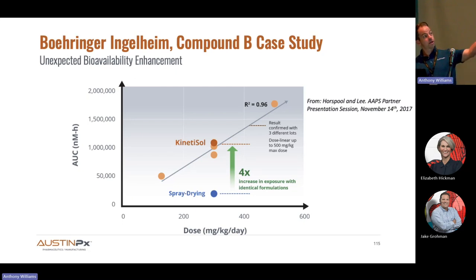But the surprise result of all of this: we were just asked to solve some practical problems. The surprise was when they took our KinetiSol formulation, which was quantitatively identical to the spray dry dispersion, and dosed it at the maximum dose that they were able to administer from spray drying, they got a 4-fold increase in exposure. Obviously, there was some error in dosing or in the study, so they dosed it 2 more times and got the same result. So in triplicate, they demonstrated that the same formulation produced by KinetiSol provided a 4-fold increase in exposure over spray drying.